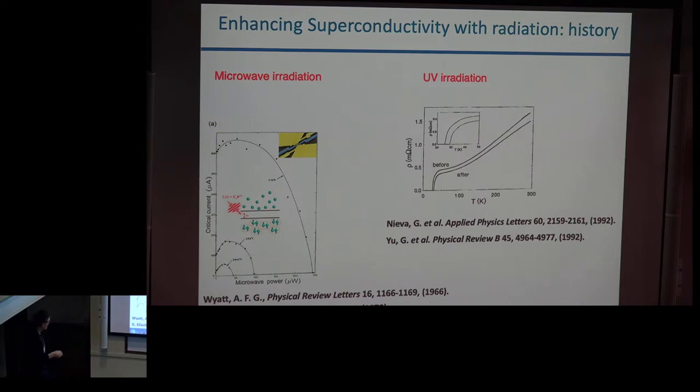And this is explained by Eliashberg's theory, because by heating up the quasiparticles without destroying the Cooper pairs, you reduce the density of quasiparticles at the 2 delta energy, and the system likes not to have too many quasiparticles at 2 delta.